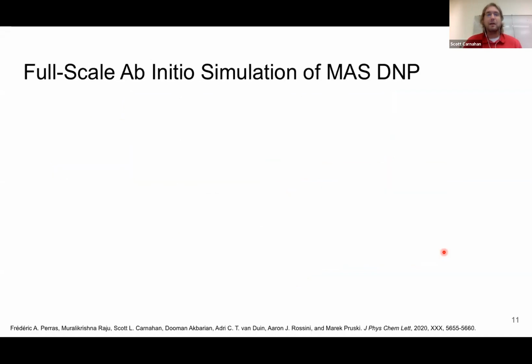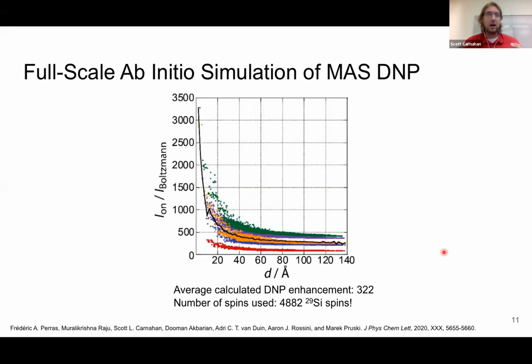Recently, Fred Perras over at Ames Lab had a project where he calculated DNP for a number of different systems, one of which was gamma radiated quartz. And what's kind of special is he was able to reproduce the DNP enhancement that we were able to get experimentally. He used a system of about 5,000 silicon-29 spins, which for an ab initio system is extremely large. What you see with his calculation is that silicon-29 spins in close space to electrons get very well hyperpolarized, and then as you get further and further away, it reaches about an equilibrium. The average DNP enhancement is what we're going to see when we do our NMR experiment.